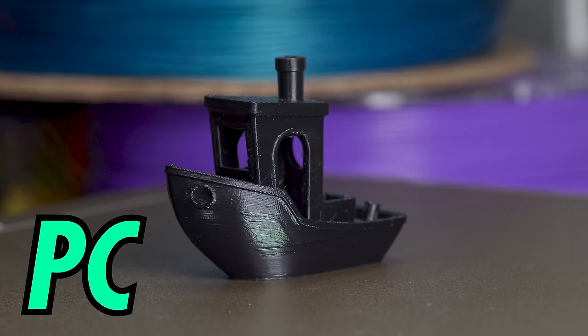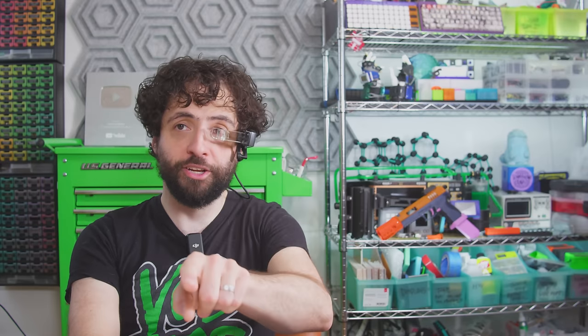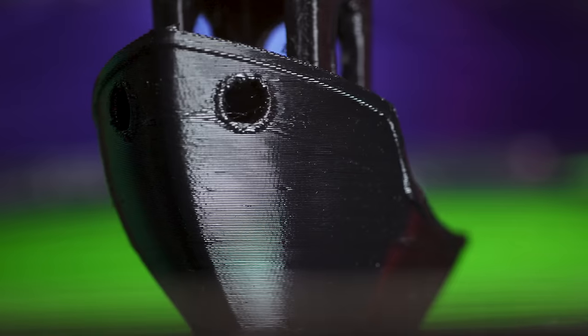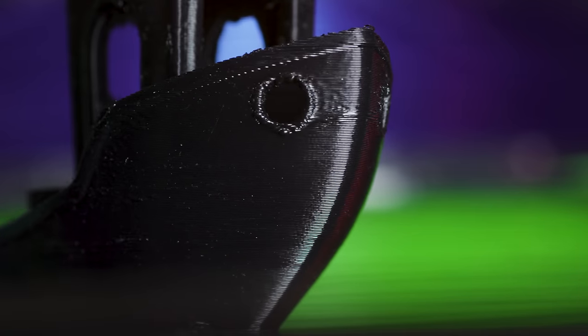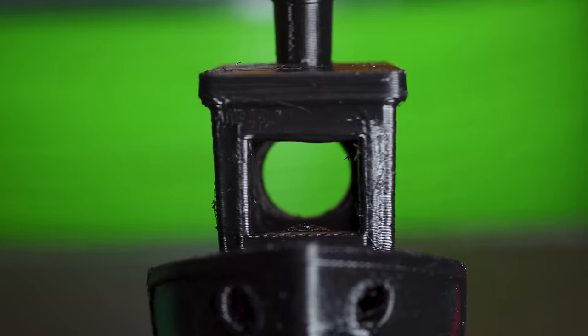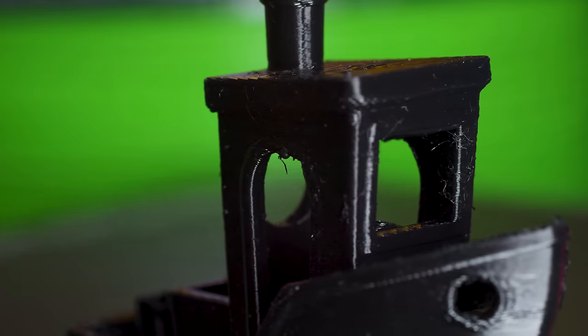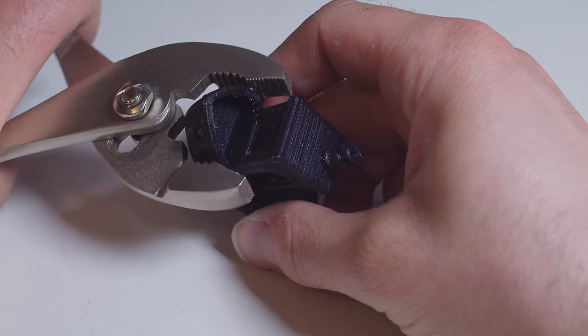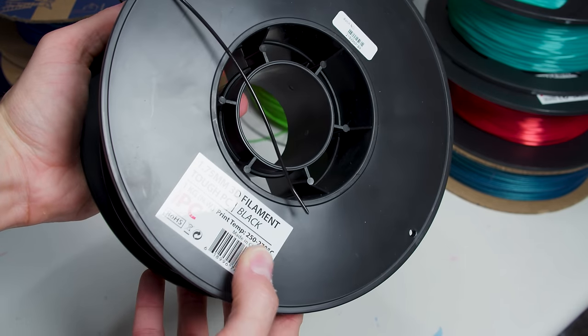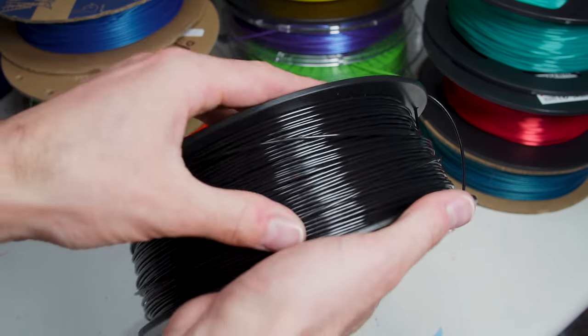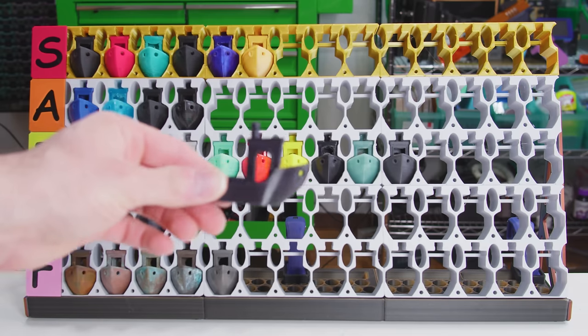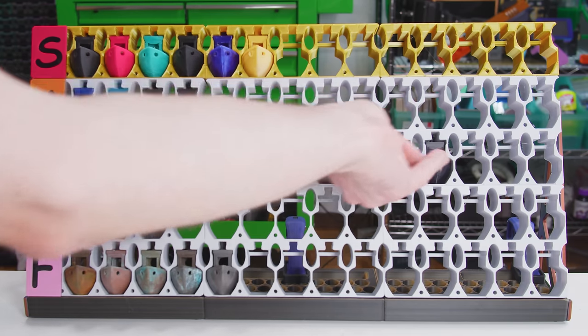Next up, PC. Not political correctness. Polycarbonate. Although, if there is a politically correct filament, I definitely want it for that every filament episode. With bulletproof toughness and a glass-like sheen, this is literally bulletproof glass. Printed polycarbonate won't actually resist small arms, but it is one of the toughest, stiffest filaments, and if you do break it, it doesn't shatter like PLA. Polycarbonate gulps up moisture almost as thirstily as nylon, and it is one of the slowest printing filaments. It also prints hotter than 300 Celsius, but once it sets, you have to heat the model to almost 150 degrees before it starts to soften. I'm gonna put polycarbonate in B tier. It is the beefiest standard filament, but those numbers can be real overkill. It's just too much work for what's usually a gratuitous upgrade.